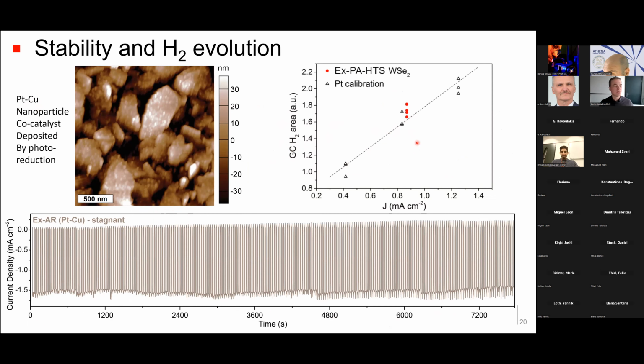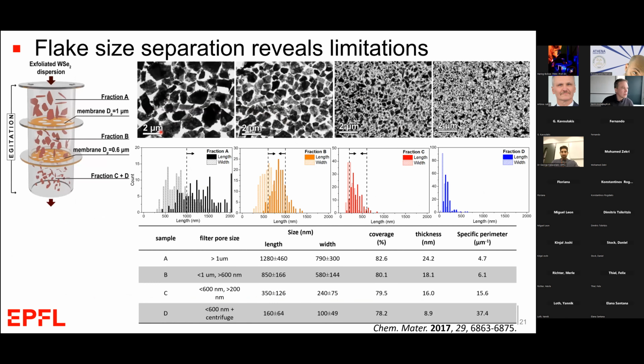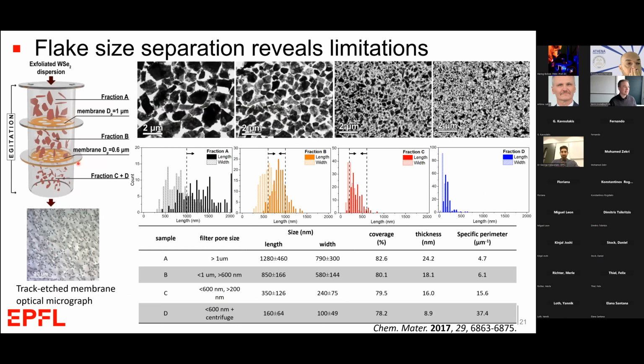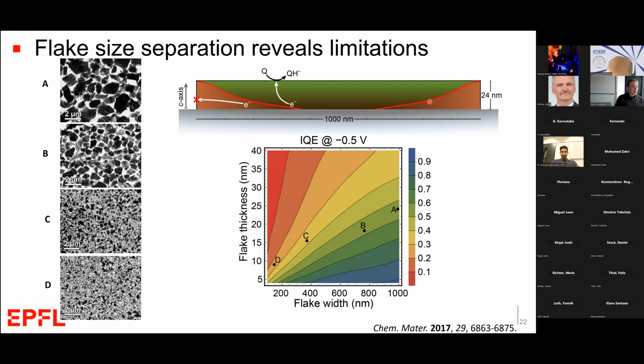So to extend this work and even improve the performance, we've done a lot of investigation on the effect of, for example, the flake size. In this work, we used track etched membranes and this sort of filtration system to isolate samples of these tungsten diselenide nanoflakes at different sizes. Together with an understanding of the sacrificial and hydrogen evolution performance of these different sized flakes, we were able to develop a model of charge carrier transport and recombination that gave us some insight into the limitations of the performance of these flakes. So let me just expand on this for a second.